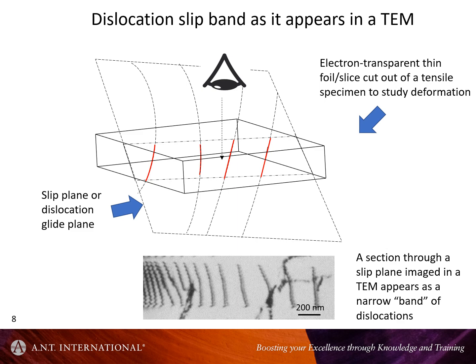I think where the ambiguity comes in, and this is where I really want to emphasize this now, in calling these things slip bands, is that typically people will observe dislocation slipping on a slip plane in a TEM foil, which is really a slice through the material. So you're taking a thin slice through the material, and when you look down on the slip plane, what you actually see are these segments of the dislocation having cut off the rest of it. And this then gets called a slip band. I'm not sure that's exactly the right terminology, but we'll call it a slip band for the sake of argument, even though it's not particularly correct.